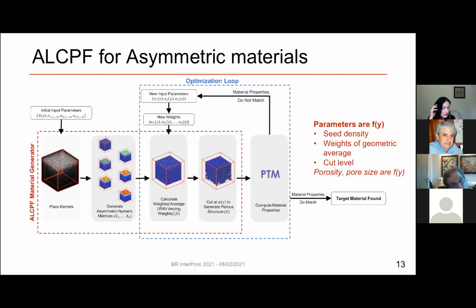And in this case, our asymmetric material has a gradient and difference in just one direction. In this case, it's direction Y. And it is different from what I just described for homogeneous materials in 4 important ways. First one, the Poisson field that you see here is not constant throughout the domain. So the density is a function of Y. So this is the Y dimension. So you see much denser kernels here than closer to the bottom.